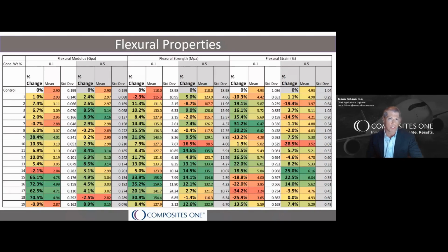Now, throughout, we've highlighted the results with colors for quick interpretation. So if you look at that 0.1% loading for flexural modulus, you'll notice significant improvements highlighted in green for samples 9 and 15 through 18, with results as high as 72%. Now, if you look at those same samples for flexural strength, you'll see that all 5 of those samples improved the strength as well. Now, if you move a little bit more to the right and look at the detail at the 0.5% loading, you also notice many more samples that improved flexural modulus. However, the improvements were not as high as the 0.1% loading. So with that in mind, it's probably good to introduce the concept of statistical significance on the next slide.